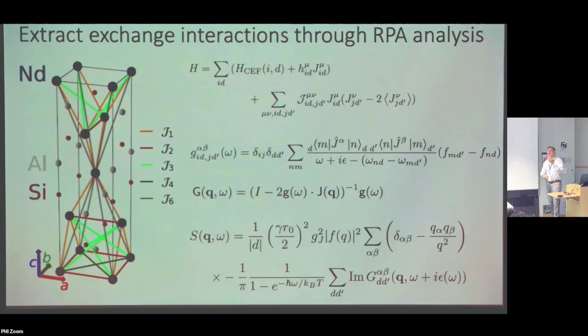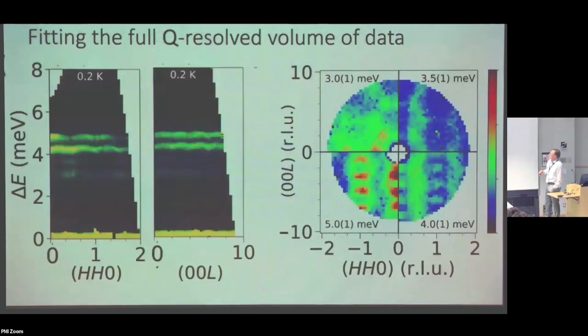Now, in the case of these metallic systems, in general actually, there has to be some approximation, which is the RPA decoupling. So it's not exact in that sense, but it may be accurate enough to get a good estimate of the exchange constants coming out from that. So then this is now back to the experimental data, and what Chris basically did was a pixel-to-pixel comparison between the calculated dynamic correlation function and the measured dynamic correlation function, and then really wandered through phase space for these many parameters to try to reproduce the entirety of this data set.